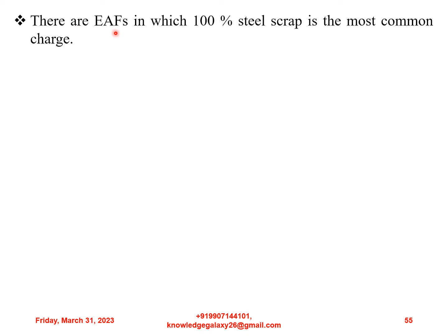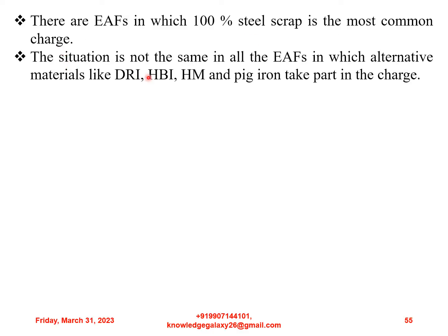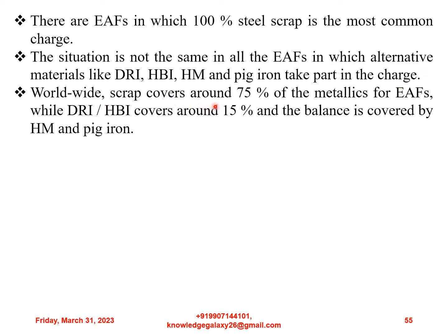There are electric arc furnaces in which 100% steel scrap is the most common charge. The situation is not the same in all electric arc furnaces, in which alternative materials like DRI, HBI, hot metal and pig iron take part in the charge. Worldwide, scrap covers around 75% of the metallics for electric arc furnaces, while DRI and HBI cover around 15% and the balance is covered by hot metal and pig iron.